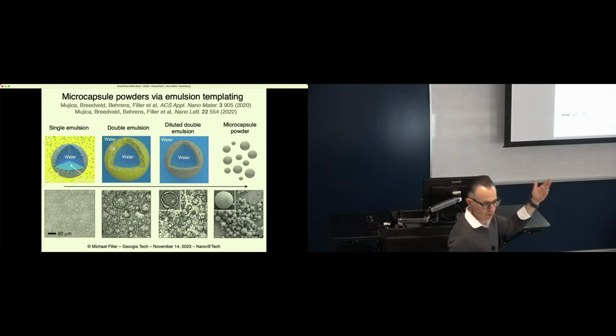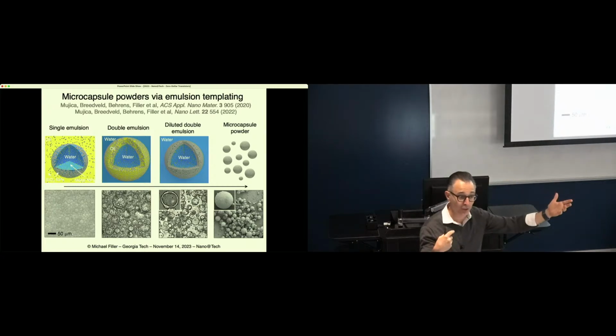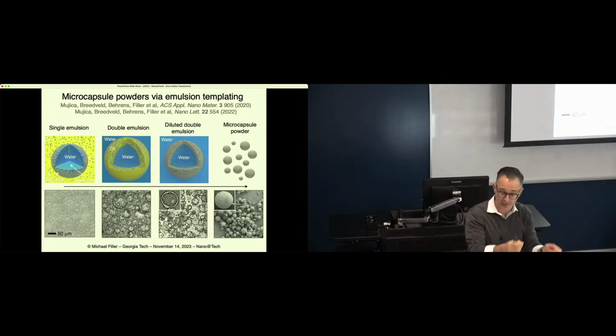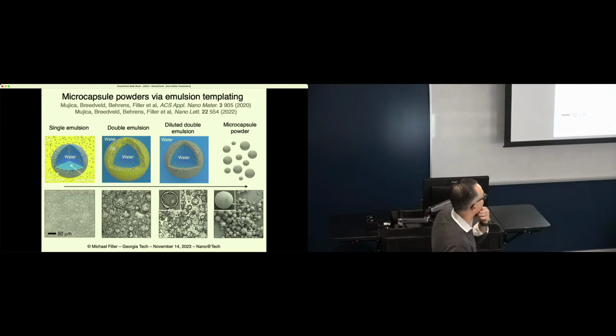You do a second emulsification, where now you have a continuous water phase, and you can start to see what's happening in that second image. We're going to have the metal particles still in the middle. The silica particles will start to be compressed in the oil shell, and then you have this continuous water phase. If you're smart about choosing the oil and it's soluble in water, it'll start to go into the water phase and leave and coalesce the silica particles into the shell. And that's kind of what happens. And you have to dry it, and you end up with a powder that looks like that.